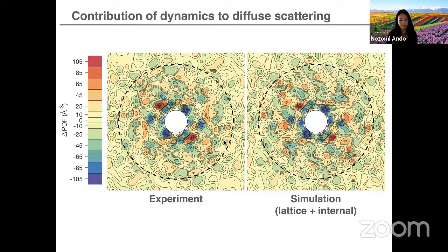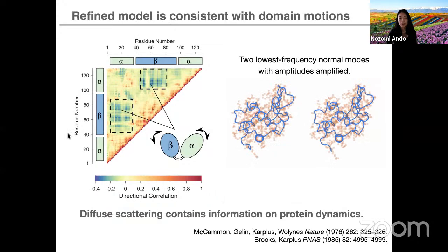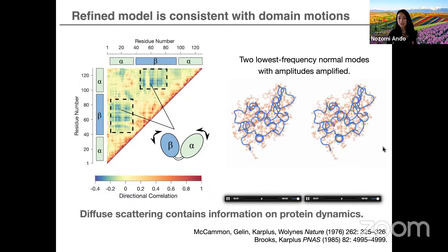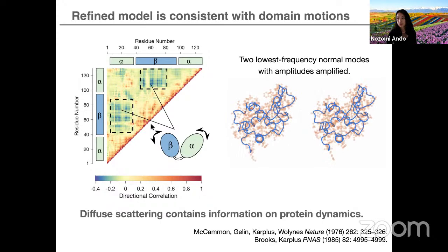And if we look at what model is refined by the protein dynamics model, here on the left, we can see that there are very clear anti-correlated motions between the two domains of the lysozyme, which had been predicted by other biophysical methods. This is more easily visualized in terms of the normal modes. Here we have the amplitudes really exaggerated, but showing that clear anti-correlated motion, explaining both the B factors as well as the diffuse scattering, which is really exciting.